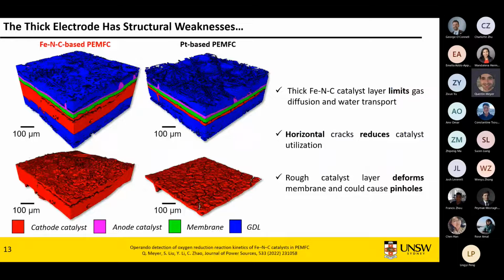So as I was saying, this comes straight down from here in the Tyree building. What we've got is an iron nitrogen carbon electrode, where basically you have a gas diffusion layer, a membrane, and then I've segmented only half the cell. So the cathode catalyst layer is between 100 and 180 microns thick. That's the material in red over here. That's very thick, with all sorts of interesting problems because of its thickness. It's actually very hard to diffuse gases through. The way it dries also gives you some interesting problems.